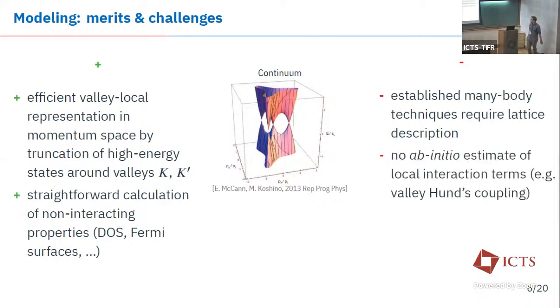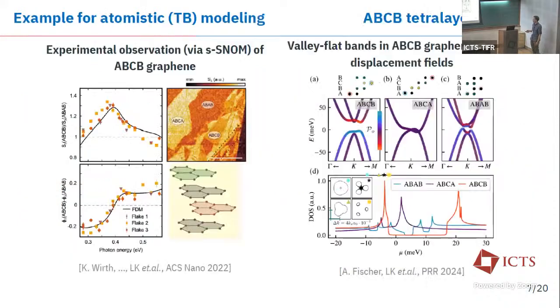And the other disadvantage of continuum modeling is that it's hard to do ab initio estimation of local interaction terms. For example, a valley Hund's coupling, so some kind of interorbital coupling between Wannier functions or states corresponding to different valleys, is difficult to motivate in a continuum setting because you don't know which real space wave function actually corresponds to those states you're looking at.